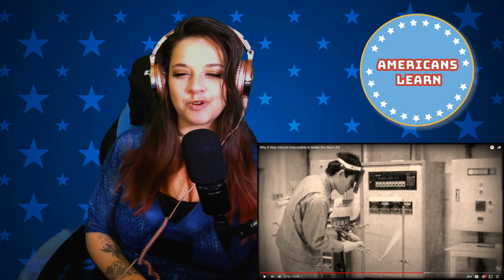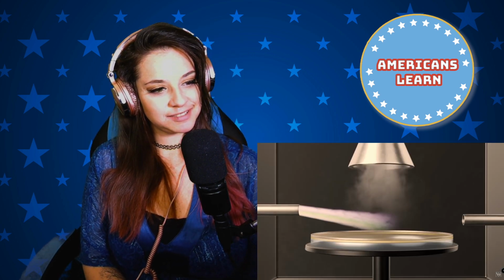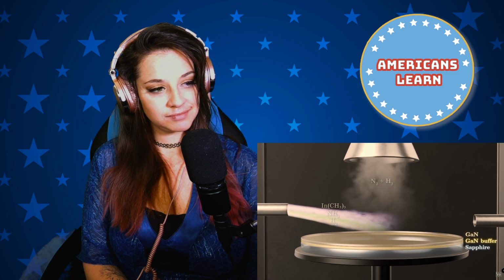And he was right. His ability to customize his MOCVD reactor allowed him to use brute force, adjusting the reactor to pump as much indium as he could onto the gallium nitride in the hopes that at least some would stick. To his surprise, the technique worked, giving him a clean indium gallium nitride crystal. He quickly incorporated this active layer into his LED, but the well worked a little too well and overflowed with electrons, leaking them back into the gallium nitride layers.